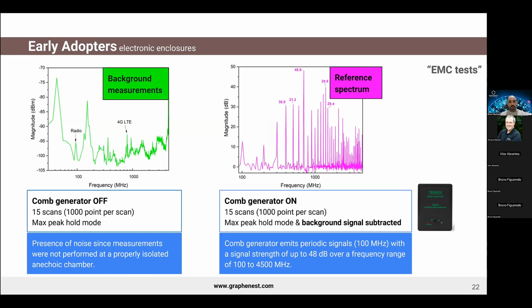So we always start this test by collecting the background signals. In this case, the comb generator is completely shut off, so without emitting any signal. So we just have the spectral analyzer collecting the background measurements. As you can see on the green plot, we could see some radio and some 4G networks. Again, this happens because we were not making measurements in a properly isolated anechoic chamber, so any kind of signal was observed by the spectral analyzer.